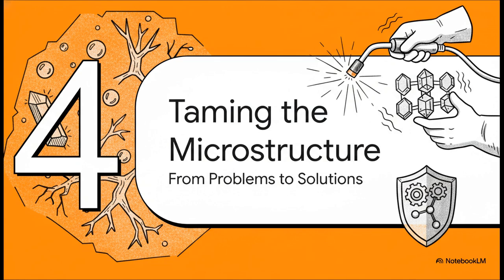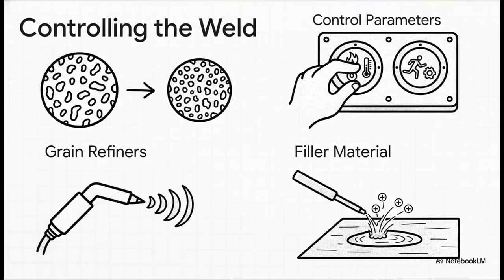Okay, so we've seen the bad guys at the microscopic level. We've got porosity, these weird dendritic structures, and this nasty liquation cracking. So how do welders and engineers fight back? How do you actually tame this chaotic microstructure? Well, they fight back with science. You can add what are called grain refiners, things like titanium or boron. They act like little seeds, encouraging lots of small, strong, interlocking crystals to form instead of big, weak ones. You can also meticulously control your welding parameters, like heat input and travel speed. You can use advanced techniques like pulsed current welding. And, this one's huge, you choose the perfect filler metal, one designed to change the chemistry of the weld pool just enough to make it more resistant to cracking.